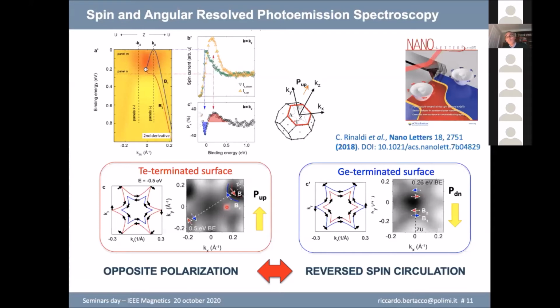But when you move to the germanium terminated one with the polarization pointing downwards, it's the other way around. You see that in the outer bands, the circulation is counterclockwise, and in the inner one it is clockwise. So it's exactly the opposite of what was found here. And this was the demonstration that, okay, it works. The original calculations by Silvia are really observed in practice, which means that if you reverse the ferroelectric polarization, you reverse the spin texture.